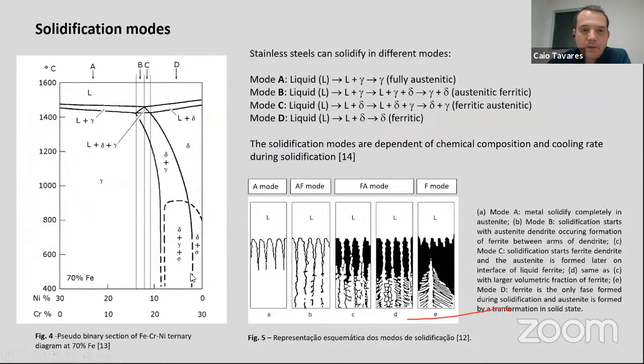So basically, the stainless steels solidify in 4 different modes. We say mode A, that is here. When the stainless steel solidifies in this way, you have a full austenite microstructure. In mode B, you have austenite and ferrite microstructure. Most of it is austenite, but you also have ferrite. That is this mode. In mode C, you have more ferrite than austenite. And in mode D, you have 100% ferrite. So it is defined this way.